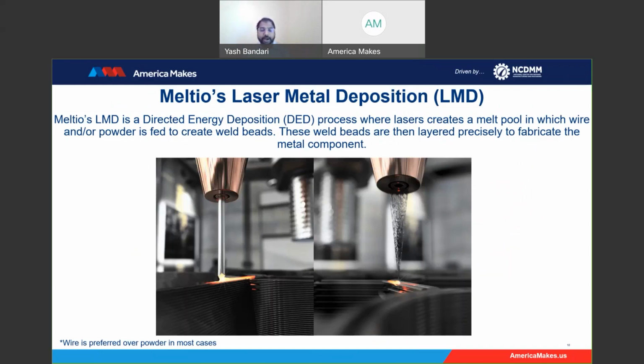This is a technology under DED, directed energy deposition, and the process is very simple. LMD is not new anymore. It has been in industry for more than 20 years, but primarily powder has been used as the feedstock. In additive manufacturing, you can also use a wire as the feedstock, but there's no technology which can use both of them independently or simultaneously, because both of these feedstocks have advantages. So Meltio developed a technology where you can feed both wire and powder independently or simultaneously, thereby leveraging the advantages of both wire and powder inside a single system.